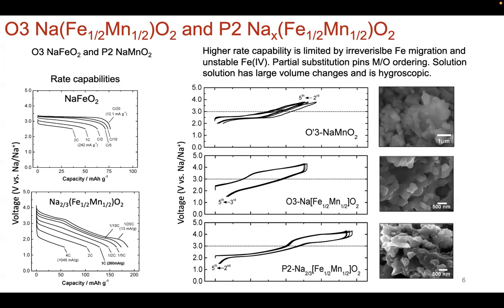The other thing to note about this plot, if you look at the galvanostatic cycling, voltage as a function of, well, doesn't really matter, capacity. But what you see is, unlike the layered materials of lithium-ion batteries, what differences do you see here that you don't see for the layered materials that we've talked about? What differences do you see in these galvanostatic cycling plots for the sodium-ion cathode materials that you don't see for lithium-ion batteries, particularly for layered materials?